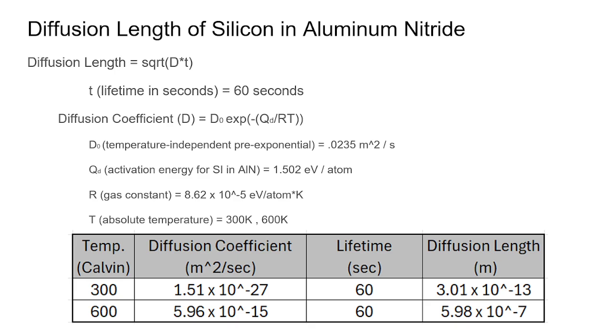So looking at the bottom table, similar to the previous slide, at a temperature of 300 Kelvin, the diffusion coefficient would be 1.51 times 10 to the negative 27 meters squared per second. The lifetime, similar to the previous problems, would be 60 seconds. And plugging those two values into the diffusion length formula, you would get a length of 3.01 times 10 to the negative 13 meters.